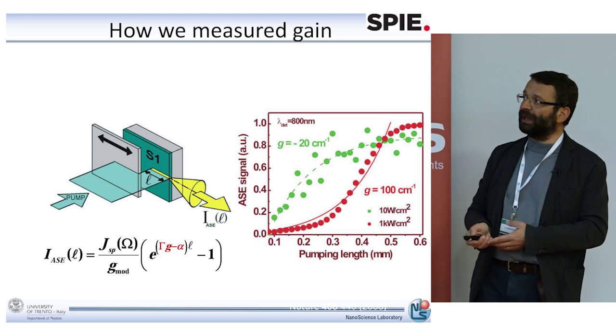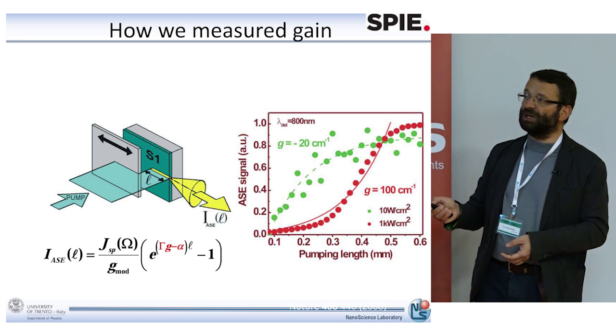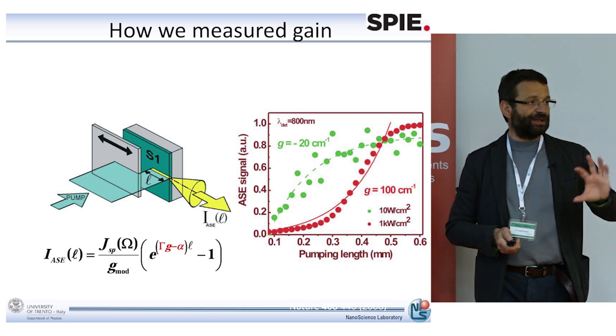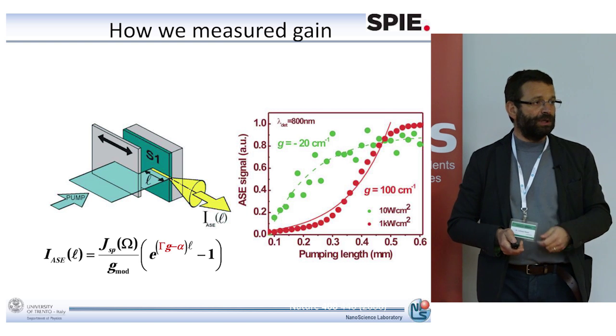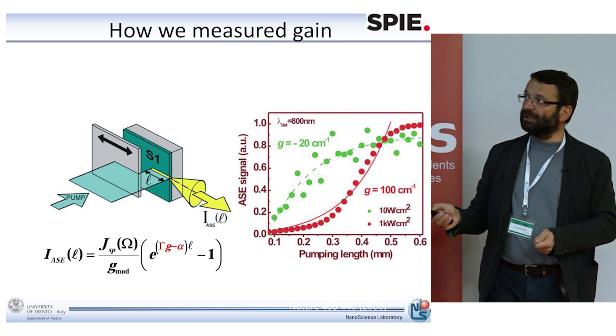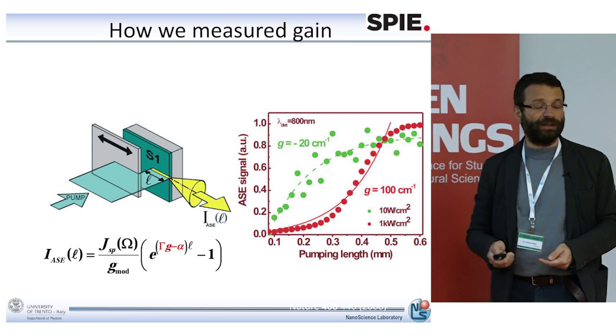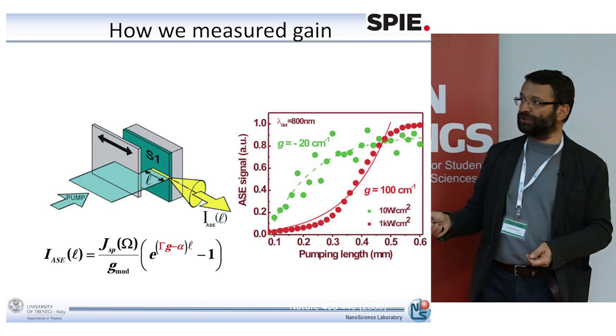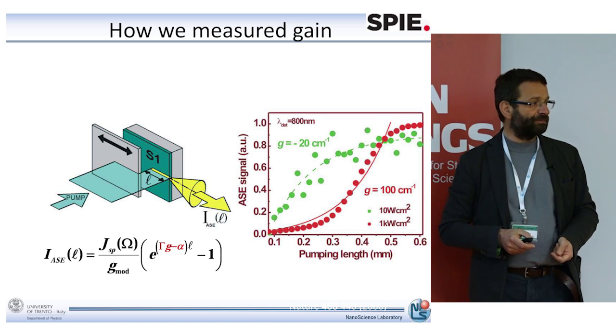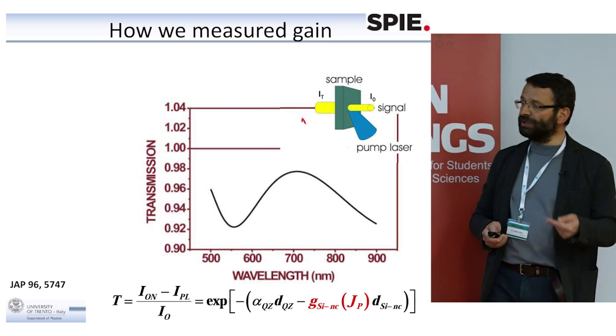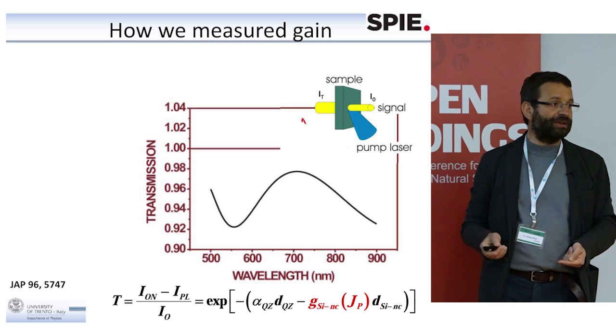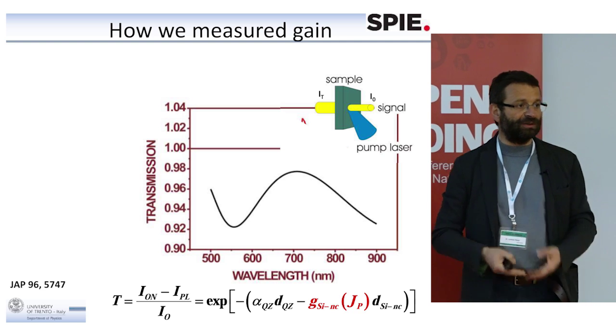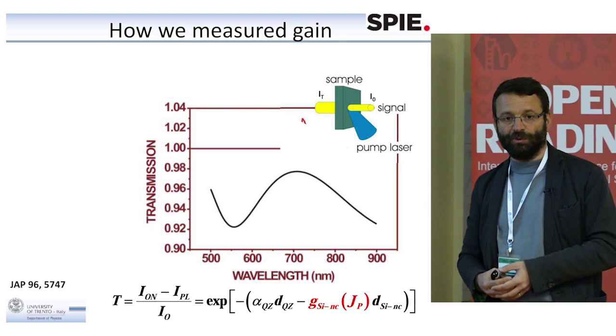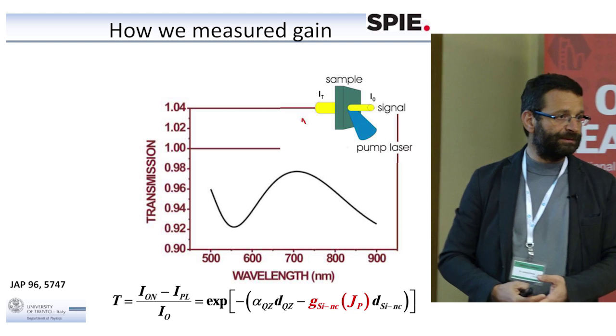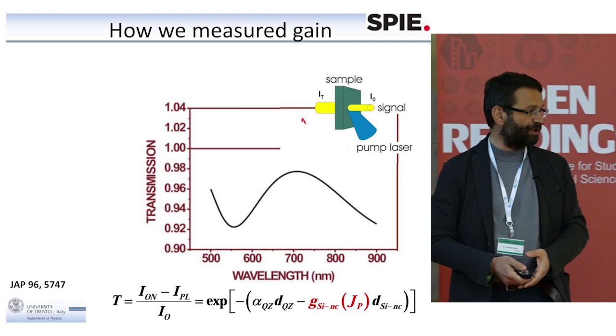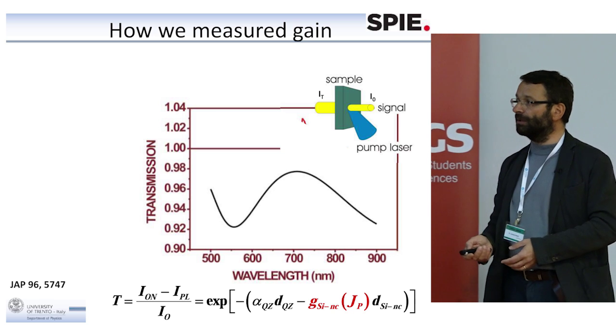So here is a transmission spectrum. We have a film of nanocrystal on top of a quartz layer. The quartz is transparent, so most of the light is going through. You get the absorption in the nanocrystal. But since the quartz and the nanocrystal have a different refractive index, when you measure the transmission versus the wavelength, you see an interference fringe. You see that you have absorption because the transmission is lower than 1. So this is a typical semiconductor. You take a film, you transmit some white light, and you know that some light is absorbed. And since the thickness is small, you get interference fringe. Nothing specific, nothing particular here.